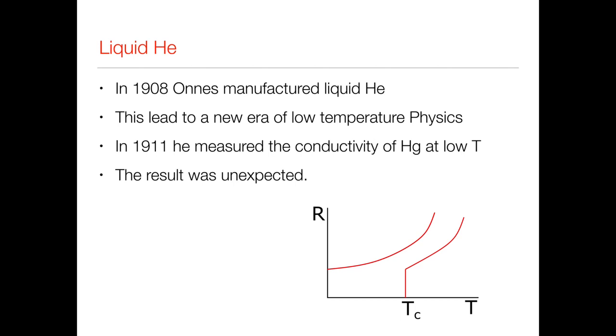Now, in 1911, Onnes tried to do this experiment. He thought, well, let's see what happens. And he looked at the conductivity of mercury at low temperatures. The result was completely unexpected, because as he lowered the temperature to a critical temperature, the resistivity dramatically dropped. Tc for mercury is about 4.2 Kelvin. As you got to 4.2 Kelvin, the resistivity was so low he couldn't measure it. He didn't have the apparatus to measure it. So to all intents and purposes, it had dropped to zero. And that's what we saw in this behavior here.